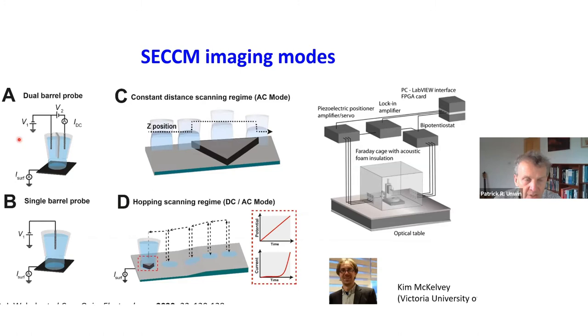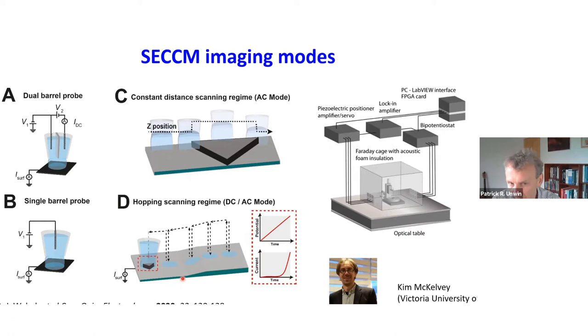The dual barrel probe was our original invention, and it's really useful if you have a surface comprising insulating and conducting material, because you need a different way for the droplet to sense the surface. We apply a small bias between two quasi-reference counter electrodes in a theta pipette, and the conductance current changes when the meniscus lands on the surface. Both techniques build up a map of the dynamic properties of the surface and also track the topography — we can do both topography and activity synchronously.